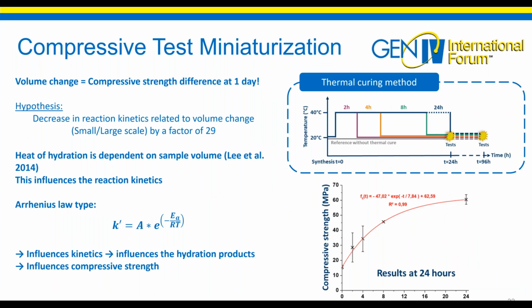Work by Lee et al. has shown that the heat of hydration depends on the volume of the sample. They have also shown an impact on compressive strength. Based on the Arrhenius law, which describes the rate constant of the reaction as a function of the activation energy and the temperature, an increase in temperature increases this constant and thus the reaction kinetics. Thus, the reaction kinetics depend on the temperature. By increasing the temperature of the sample, the reaction kinetics should be increased, and therefore the amount of binder phase present, and the mechanical performance also. The development of mechanical performance is linked to the amount of binder phases present.